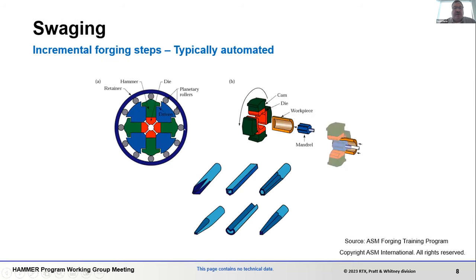Again, very, very common. Using a swaging kind of tool or process where you have multiple hammers and these hammers are coming in incrementally as you feed material into this work area, and you can start to make very, very complex configurations of these kind of shapes, tapers or shafts for, say, gas turbine engines. So again, it's not using a full closed die. It's actually using incremental deformation to do the straining where you need it. But that straining where you're needing it does mean that you're actually doing metallurgical work in those areas, and you need to be taking that into account and understanding that from a microstructure and processing path and property perspective.